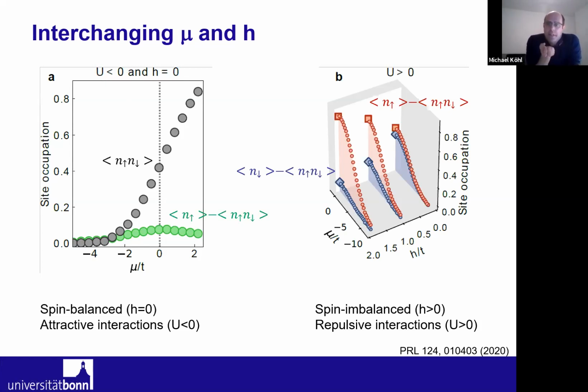Now let's reverse this. Now let's go to the repulsive side and find out about the spin imbalance. So this measurement is slightly more complicated. So we have to create spin imbalances by hand and then measure the same property again. So here is the Zeeman field. So that's the amount of spin imbalance that we have. Here is the balanced case, 0. And at 2 we have already a significant spin imbalance. And you see the spin imbalance, so the spins are shown as the spin up and the spin down densities in red and blue here.